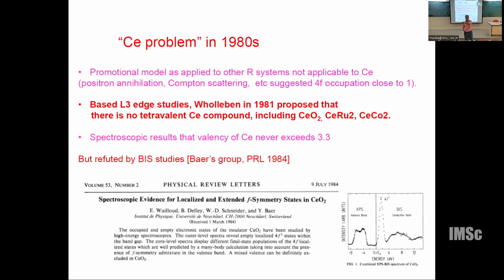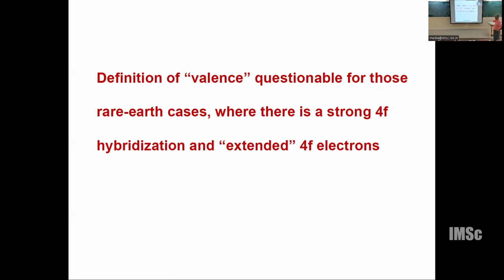Therefore, going back to the question, now you call cerium dioxide mixed valent or tetravalent or mixed valent? Because as I started with the transparency, that is the measure of 4f valency, is a measure of 4f count. Now, what do you call this? You say 50% 4f electron, 0.5 4f electron sitting in the oxygen band. Now it is 3.5. Is it 3.5? That question came up. Therefore, the definition of valence was questionable for those rarer cases where there's a strong 4f hybridization, extended 4f electron.